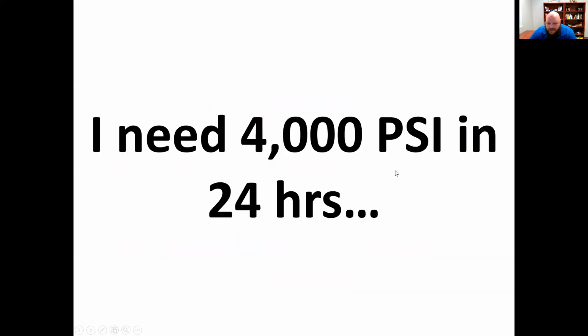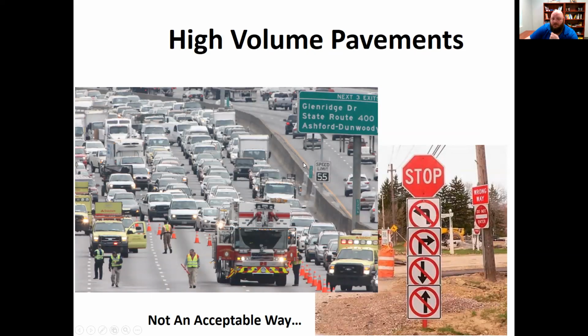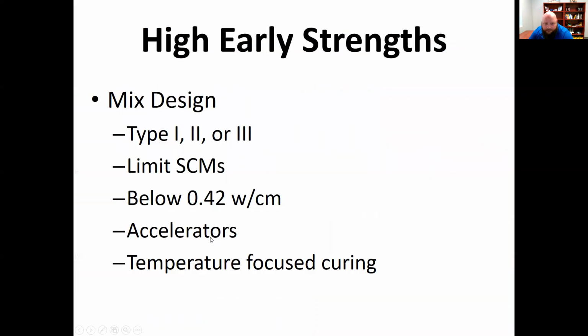So things like I need 4,000 psi in 24 hours. Well, it's not 8,000 psi, but 4,000 in 24 hours. The slope of that curve is crazy. So this would most definitely be a high early age strength mix. And realize things like high volume pavements where there's lots of rush hour traffic, you don't want to close down a lane or 2 lanes of traffic. And so a lot of times you want to use something that's going to quickly gain maybe 3,000, 4,000 psi, enough so that you can reopen that major lane of highway.